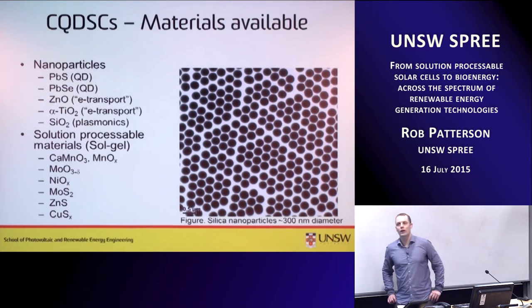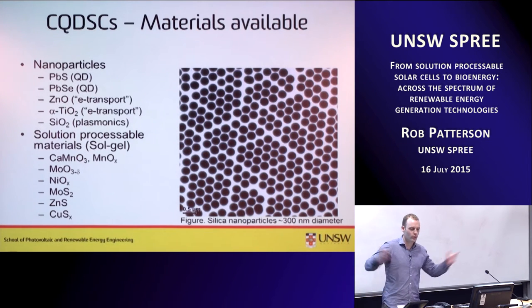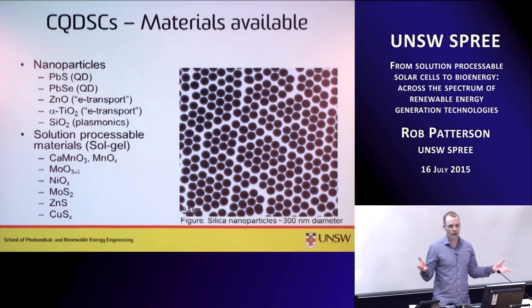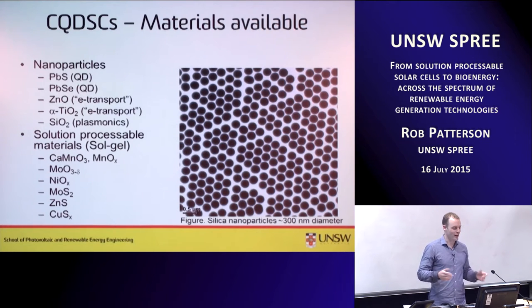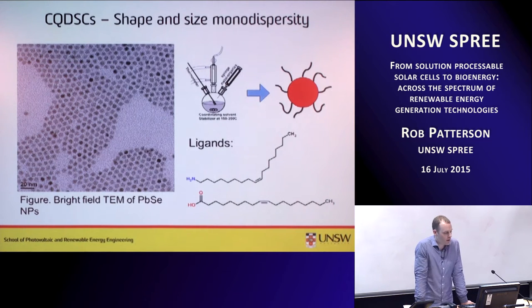So again, because we tend to do solution processing, we have access to a wide variety of materials. If you go into a chem lab and you have a shelf full of chemicals, you can almost have the whole periodic table available to you. And if you're a good chemist, then you have some opportunity to make interesting materials in a piece of glassware, which is a nice advantage. We tend to stick to lead chalcogenides so far, sulfides and selenides. But we also use some other typical materials for this type of cell: zinc oxide, titania, and silica. Here's a picture of some silica nanoparticles, which have been made for plasmonics applications. But we also have potential for other materials as well. MoS2 is a potentially interesting material. ZnS is a potentially interesting material, all of which can be made in a beaker as nanoparticles.